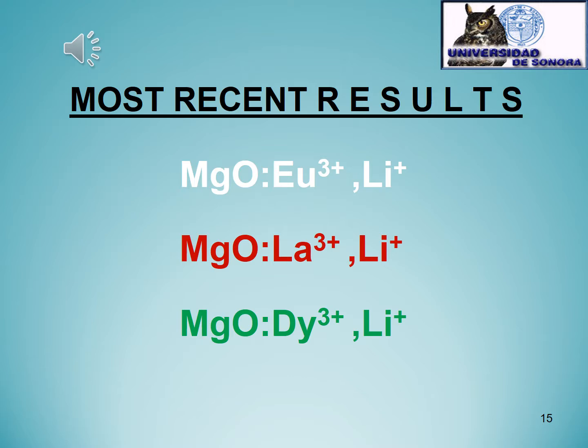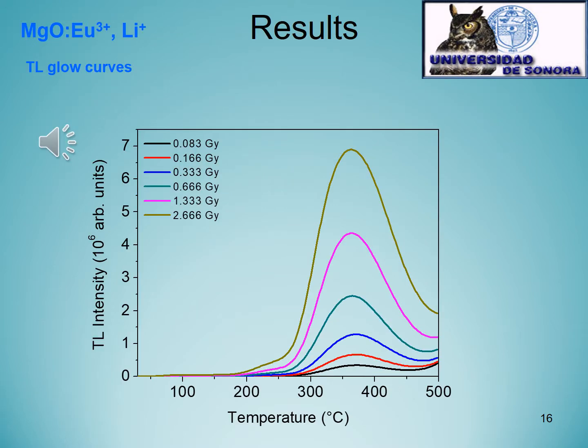In this respect, our most recent materials obtained are magnesium oxide doped with europium, lanthanum, and dysprosium, and co-doped with lithium, the 3 types of materials. One of our new materials obtained is magnesium oxide, europium, and lithium doped.